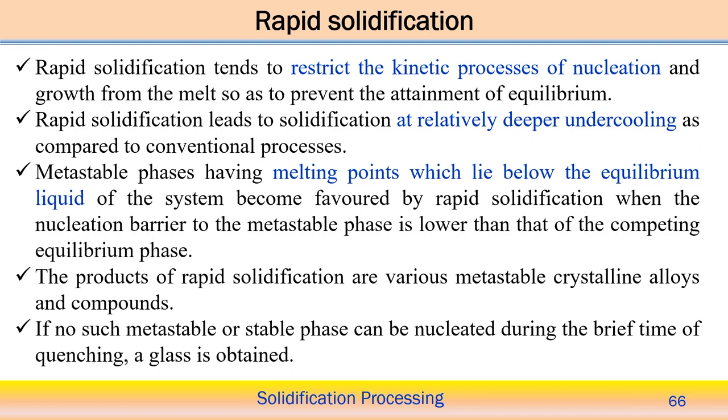Rapid solidification is also associated with some metastable phases, which have melting points that lie below the equilibrium liquidus of the system, and it is favored when the nucleation barrier to the metastable phase is lower. In this case, we can expect rapid solidification to reach that, as the nucleation barrier to the metastable phase is lower, even when competing with the equilibrium phase. So it definitely tries to create the metastable phase as compared to the competitive equilibrium phase.